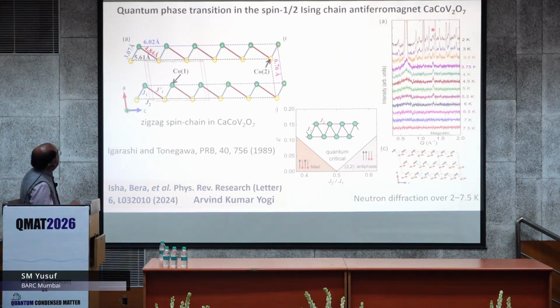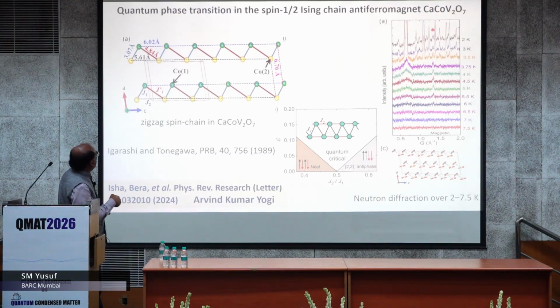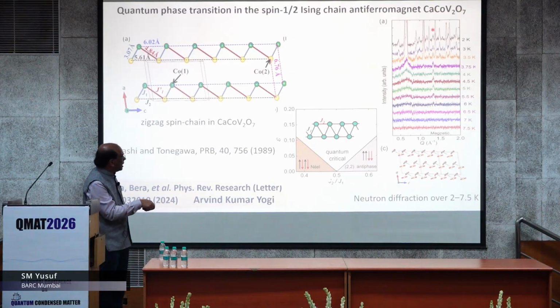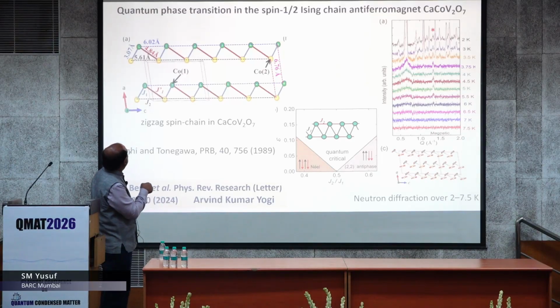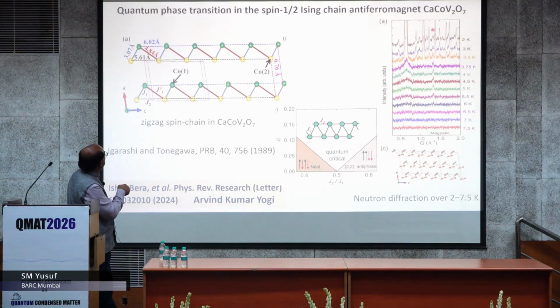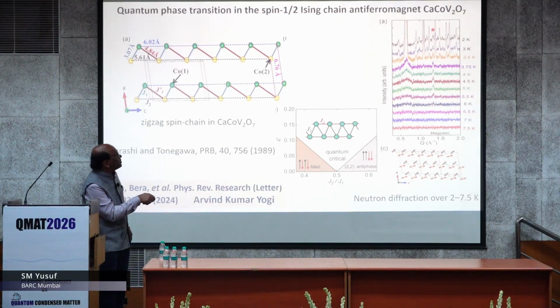Bera is very much here, and in this case you see the triangular lattice again. So first I am completing the triangular lattice series, but that was a uniform triangular lattice, but here you see the arms are not equal. See the bond length, of course non-magnetic atoms are there, oxygen there. So in this case the theoretical phase diagram depends upon J2 by J1, that is J2 is this one, by J1 this ratio, this is the quantum critical point, and on this system we have done a careful neutron diffraction study,